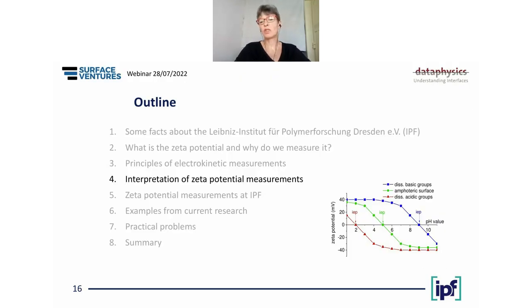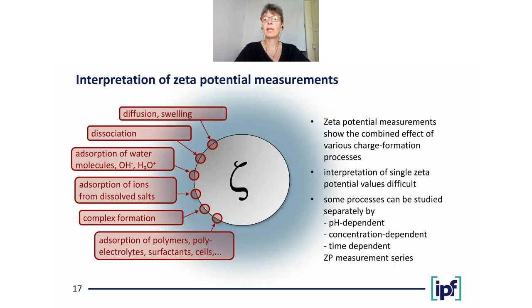So when we have measured the Zeta potential, of course, we need to interpret it because the Zeta potential itself doesn't give too much information. So I come back to this scheme I showed you already. The Zeta potential measurements show the combined effect of all these charge formation processes. That's why it's very difficult to interpret a single Zeta potential measurement, but some processes can be studied separately if we do a pH-dependent Zeta potential measurement series, a concentration-dependent series, or time-dependent series. That's why we usually don't do single point measurements, but always these measurement series.